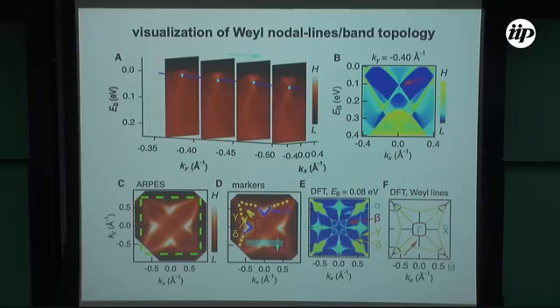So I'm showing kx for a particular ky, and then the energy cut. This is based on DFT. We expect that if I go to a ky value like this and scan kx and energy, then I'll find a Weyl node here. And then we can track that in ky by changing ky, and this is what we're seeing. So in other words, there is a Weyl node loop in this 3D Brillouin zone.